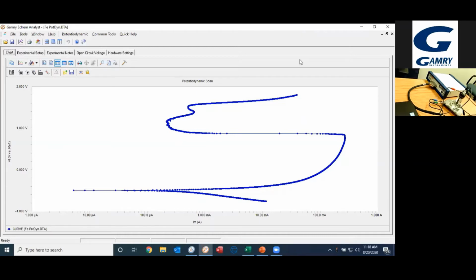But one thing to note here is that this full potentiodynamic scan is scanning nearly over 3 full volts. You have these regions here where you have a more active region and you move into more passive regions. I always think these kind of look like a river going off into the distance. The data you can get from these is more qualitative, but what we're concerned with is the data right here. This is the Tafel region. This region right here obeys Butler-Volmer. So this is the region we're going to take a look at and try to model.